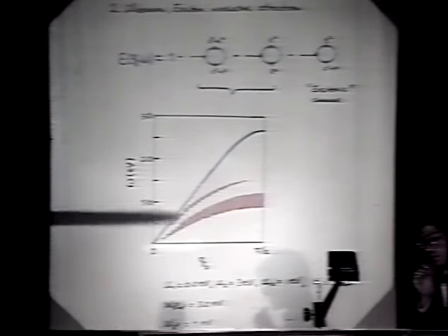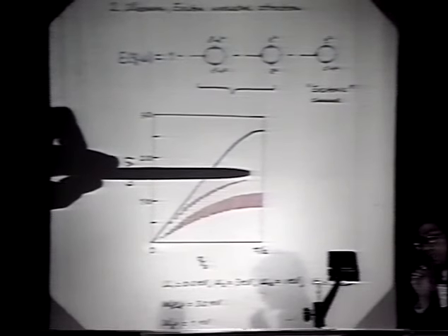Moreover, we have also considered the electronic mechanism for superconductivity. Starting with the two-band Hubbard model, we have calculated the screening of the interaction between dx squared minus y squared electrons due to the intra and the interband polarization process. The following figure is constructed where we only include the intraband polarization, and this solid blue curve is the Landau damping boundary, and the red regions are where the electron-electron interaction between x squared minus y squared band electrons is attractive. To include the interband scattering channel, usually it introduces another narrow strip of attractive region at the expense of a narrower intraband attractive region.